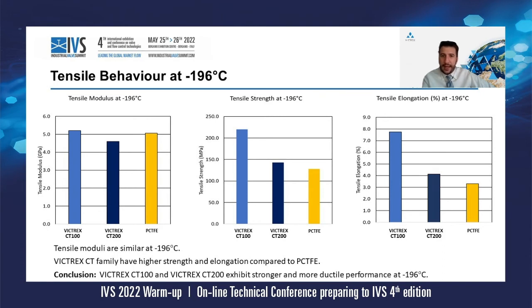This indicates how suitable a material is for sealing. While we can see there are no big differences in the moduli at -196, it's possible to appreciate significantly higher strength and elongation, especially for CT100. Remember that a more ductile material results in a more reliable seal, as it penetrates the metallic counter surface better, reducing gaps and reducing the possibility of creating a leakage path for the fluid you want to seal.